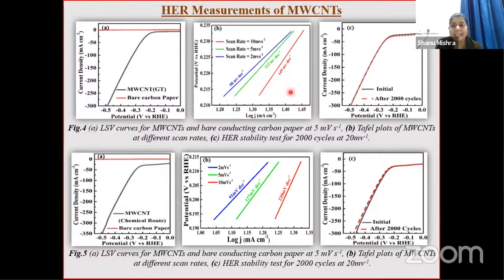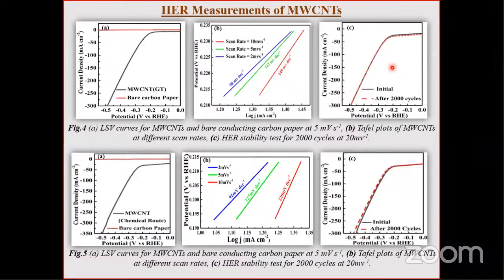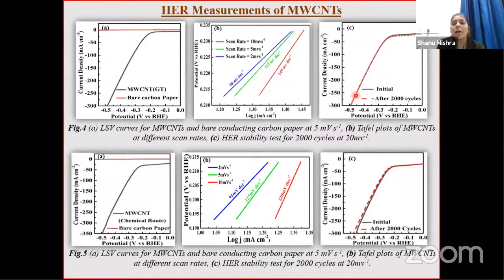For a catalyst, it's also important that it possesses high long term stability. So here we performed the stability test of 2000 cycles for both the catalysts and plotted it. There is negligible current density variation in both. After the 3 electrode measurement, we saw good performance.